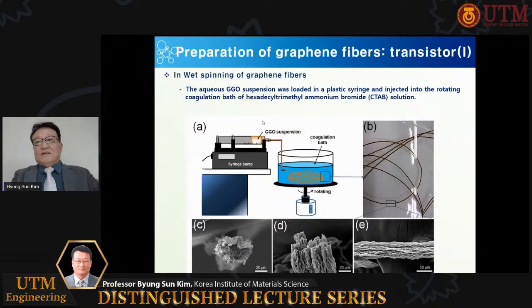Okay, I go on. In order to have improved fiber type transistors with higher electrical conductivity, stronger mechanical properties, and higher flexibility, graphene fibers are manufactured. In wet spinning of graphene fibers, the aqueous graphene oxide suspension was loaded in a plastic syringe and injected into the rotating coagulation bath of hexadecyl trimethyl ammonium bromide solution.